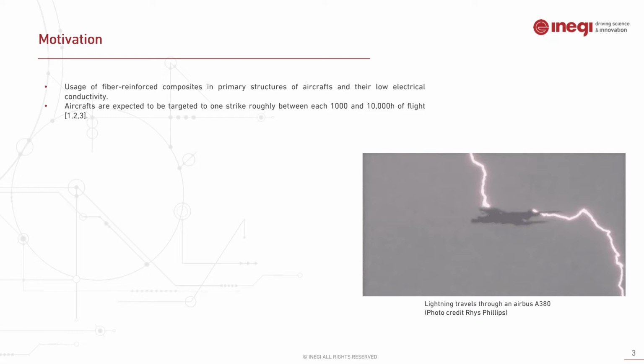Aircraft are estimated to be struck roughly once every 1,000 to 10,000 hours of flight. This means for an airliner that it corresponds to one strike per year. This can be a direct or indirect effect. In terms of direct effect, it could cause embrittlement, resin evaporation, delamination, and even the ignition of fuel vapor. An indirect effect would be damage to the onboard equipment.